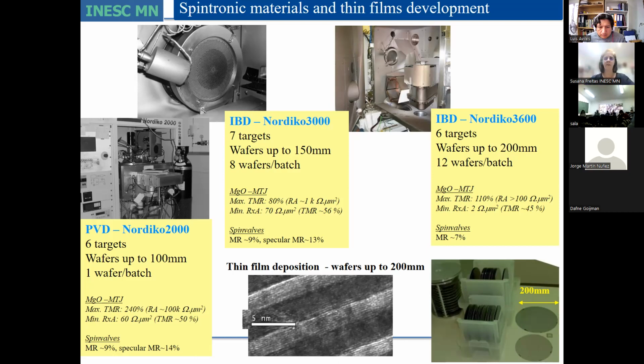So in some areas of the wafer, the time that you are using to repin the sensor is not enough. So you need to have more time or more energy or higher field or whatever. So this is a very, very relevant point that the industry is asking us to help with. And in particular, working on materials that have a narrow blocking temperature window, so they don't have so much dispersion in blocking temperature. So this is an interesting area that we have been also working on.